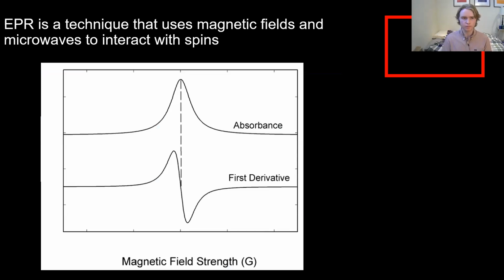So on a base level, the way that EPR, or electron paramagnetic resonance, again, works is using magnetic fields and microwaves to interact with those non-zero spin states, as I talked about a little bit earlier. So in this picture, you can see an example of what you might see coming out of an EPR. You would normally get your spectra out in a first derivative curve, as is noted here. And for those of you who are more used to an absorbance curve, you can actually just take an integral of the first derivative, and you're going to end up with something that looks a little bit more like what you'd get out of a lot of other instruments. But most people who work with EPR work with the first derivative curve, and that's just because that's the way the data is actually collected by the instrument.